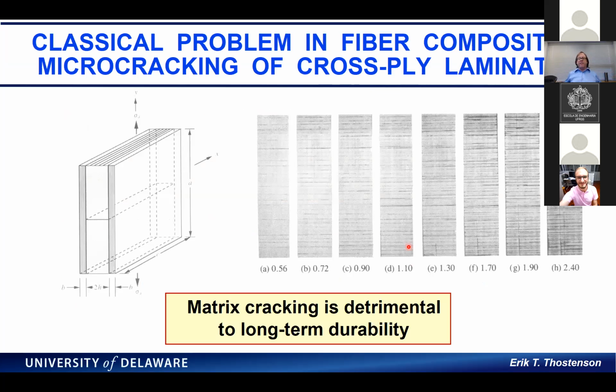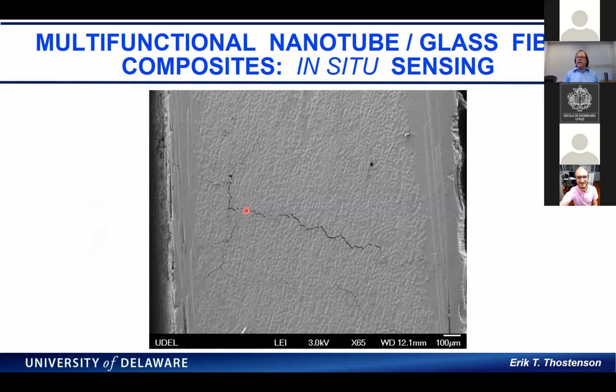And in my composites class, this is a classical mechanics problem, is that you generate these transverse microcracks in cross-ply laminates, and then eventually, as you continue to strain it at higher and higher levels, you start getting a saturation of cracks due to shear lag. And of course, this matrix cracking doesn't necessarily change the Young's modulus that much, but it's certainly detrimental to durability. So this is an example.